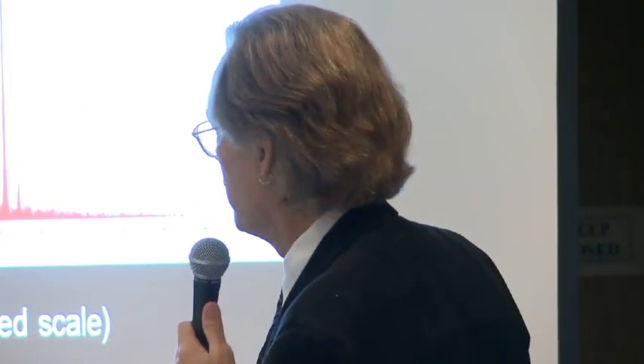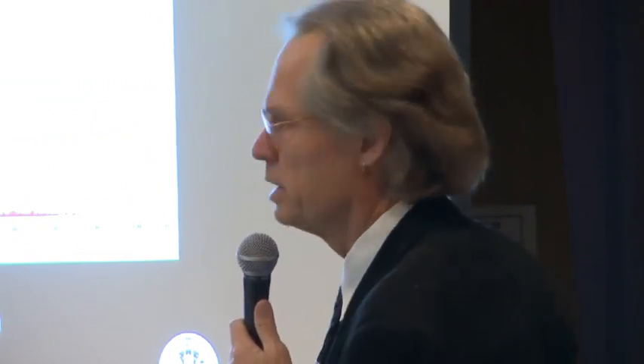The point here is we do not see zinc. Going back to the energy dispersive spectroscopy from the red layer, we have blown up the area where you should expect chromium. You can see a little chromium, but we simply cannot see zinc. When you blow up the vertical scale, the regular peaks go completely off the chart. So the signal from chromium is at the level of noise — it means there's nothing in there. Conclusion: the red-gray chips cannot be the primer paint because we do not see zinc chromate.